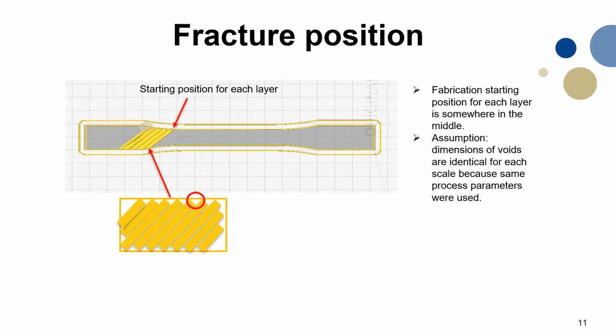And this is one possible reason to explain why some of the specimens have the fracture position near the edge of the gauge length. For each layer of the printing, the Cura software, instead of starting from the end, actually starts somewhere in the middle for every single layer. So that may cause some defects here. And we can make an assumption here: the dimensions of the voids are identical for each scale because the same process parameters were used in this case.